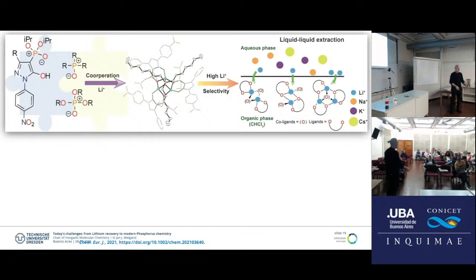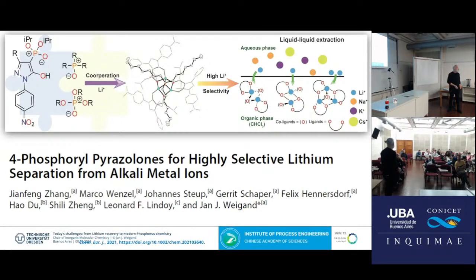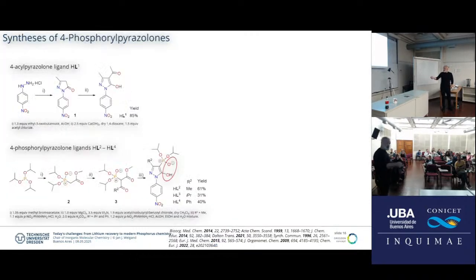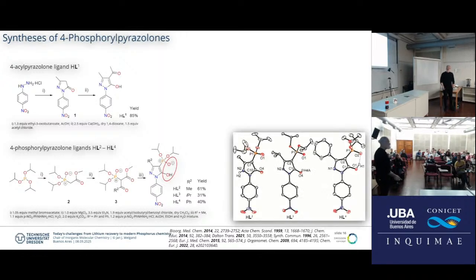And you could even use a lot of different techniques to understand, is there a trinuclear, dinuclear, the interconversion between a di and trinuclear, depending on the amount of ligand, depending on the stoichiometries and on the concentration. And you could use a lot of different kinds of techniques in order to really show that these phosphoryl pyrazolones are highly selective toward lithium. And again, here just a synthesis, which is very much related to the one we saw before. The yields are okay. And what's now interesting, this position here is protonated, and we can deprotonate.